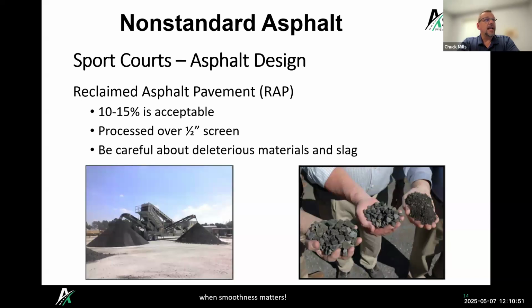When we're talking about asphalt design, you can use some RAP in it, although you don't want to use a whole lot because you have to be careful about those deleterious materials and slag being in your RAP. Typically, it's processed over a half-inch screen, so you want the smaller particles of RAP, typically limited to 10 to 15%. A lot of people will specify no RAP in the top course. So if you're doing a two-course thing, maybe there's some RAP in the base course, but not in the top course. And that's to make sure that we're not getting any of that deleterious or staining material that can happen on the surface.